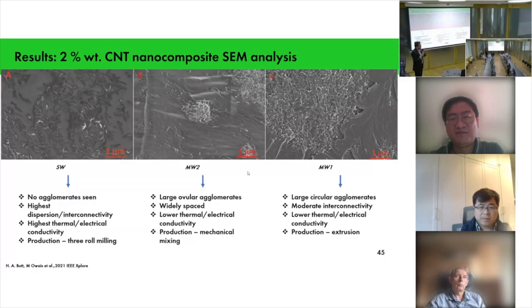Because the production method was different for single wall. It was the three roll milling technique that the industry used. So you started with master batch for single wall. They were already quite dispersed. With a multi-wall carbon nanotube, you started with powder, right? No. All three were master batches, but they use different techniques. I diluted it with epoxy. But why do you have such a bad result for multi-wall carbon nanotube then?